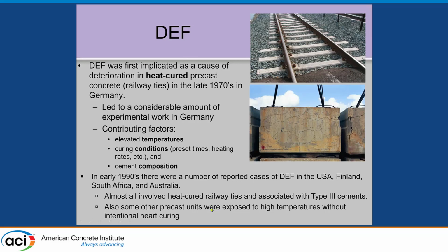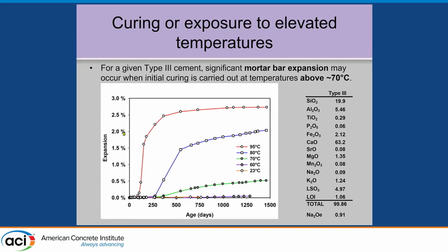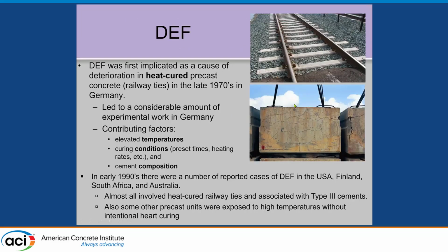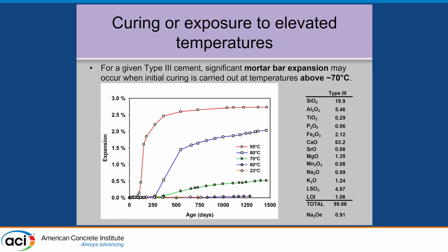And some other precast units that were exposed to high temperatures without intentional heat curing, such as this girder in Texas. There's a precast girder which cracked up before it even went into service. And people said it was ambient temperature DEF, but really it was cast in the hot sun. And I'm sure it got up to about 90 degrees Celsius inside the concrete during the curing. And so type 3 cements that perform quite well at room temperature, and these are expansion graphs versus age going out to about 3 or 4 years here.